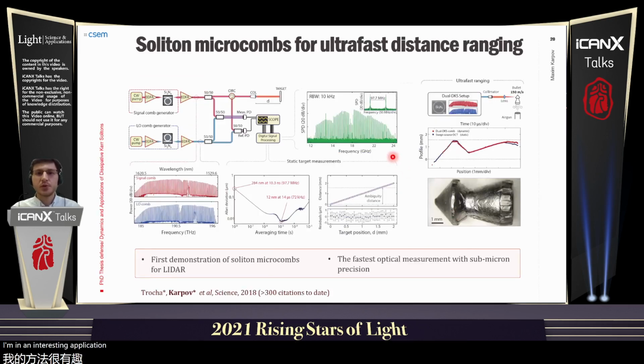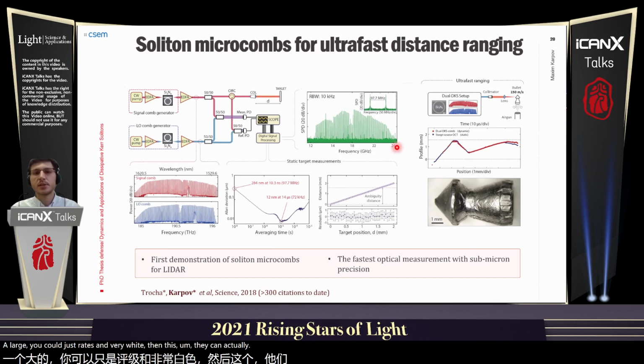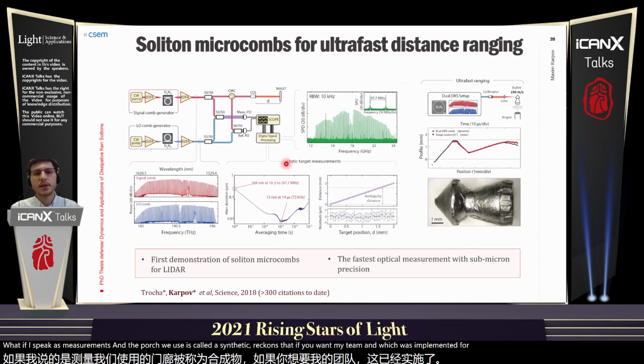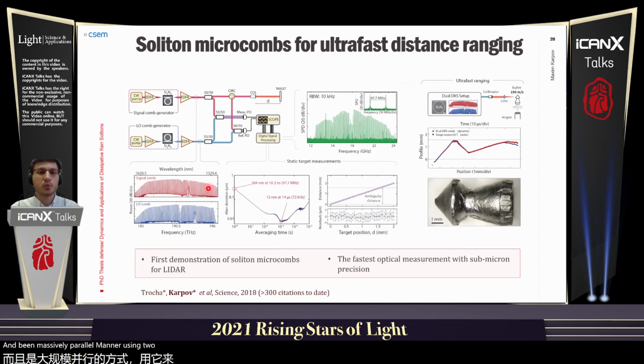Another interesting application which we demonstrated was ultra-fast distance ranging using soliton microcombs. Again, due to their large repetition rates and very wide bandwidths, they can enable very fast data acquisition of the distance, or very fast distance measurements. The approach we used is called synthetic wavelength interferometry, which was implemented in a massively parallel manner using two combs. One was used as a signal comb, and we shoot it towards the target. Each of the comb lines acquires some phase shift due to the propagation forth and back, and then we uncover this phase information using the second comb, the LO comb.